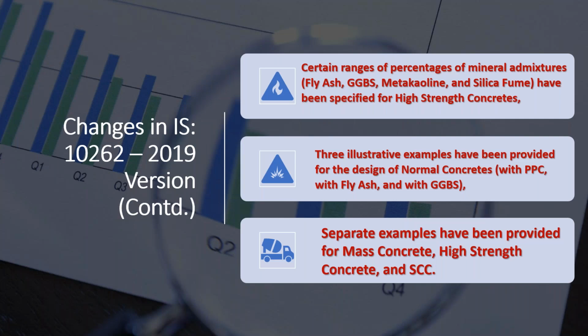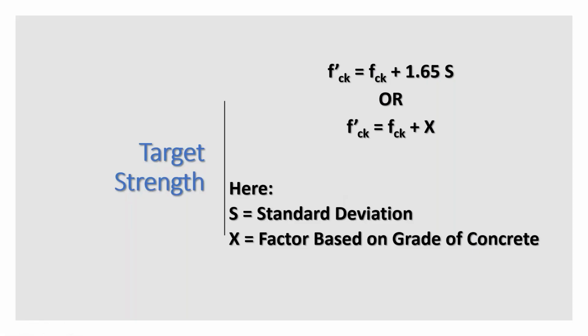The other changes are that certain ranges of percentage of mineral admixtures like fly ash, GGBS, metakaolin, and silica fume have been specified for high strength concrete. Three illustrative examples have been provided for the design of normal concretes with PPC, with fly ash, and with GGBS. Separate examples have been provided for mass concrete and high strength concrete, so in total 6 illustrative examples have been provided in the revised IS 10262. This is the relation for the target mean strength. Two relations have been given. One is f'ck equals fck plus 1.65 times the standard deviation. Another relation is provided based on the grade of concrete, f'ck equals fck plus X, for which separate tables have been given.